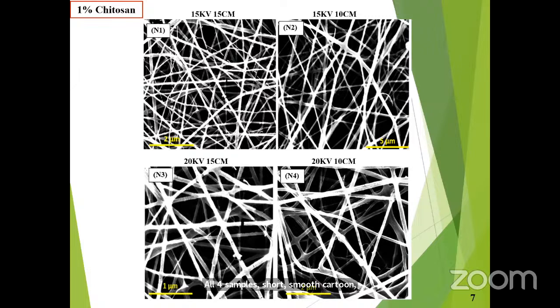Samples N1 and N2 were produced at 15 kV voltage while keeping the working distance at 15 centimeter and 10 centimeter respectively, while samples N3 and N4 were produced at 20 kV voltage while keeping the working distance at 15 centimeter and 10 centimeter respectively. And we concluded that the 1% solution smoothly produced the chitosan nanofiber.